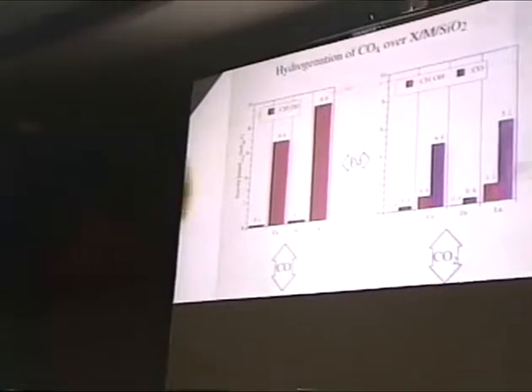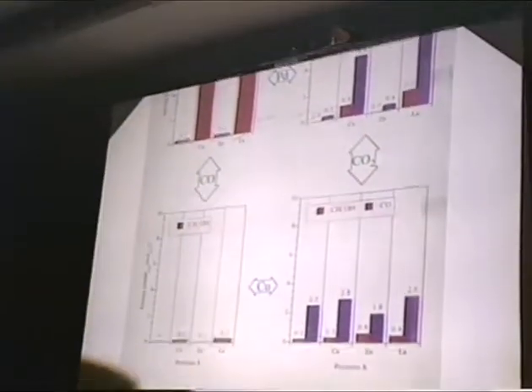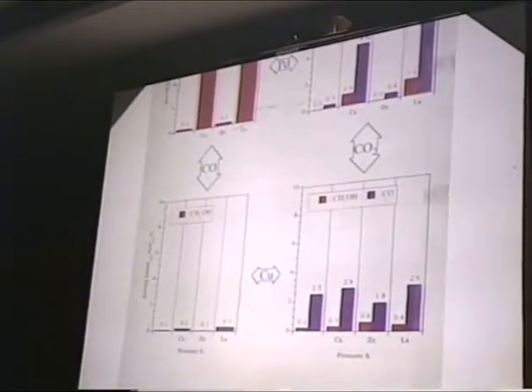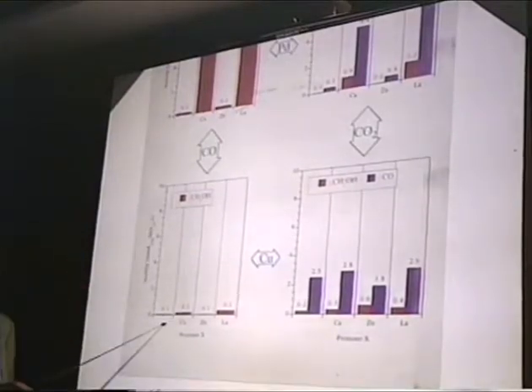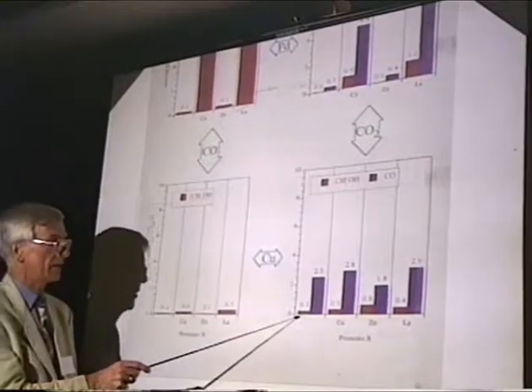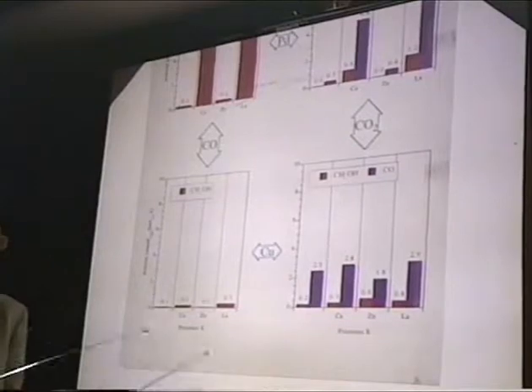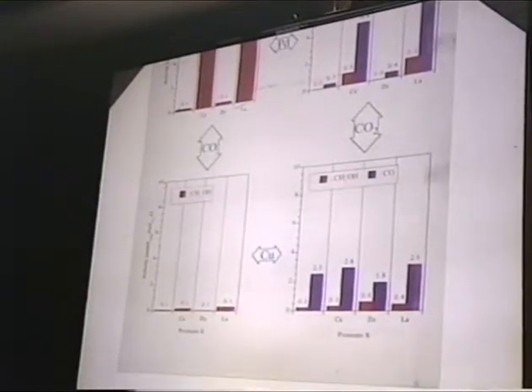And this in contrast to what you get with copper. With copper and CO, it's low. With CO2, it's higher. And in all cases, it does promote it. But the palladium absolutely is not the same as copper. It is really going through the CO, and it is heavily promoted by a basic metal oxide.